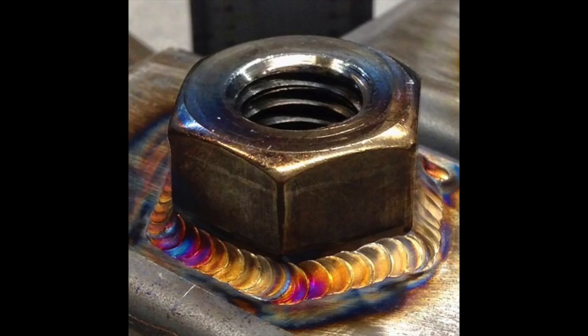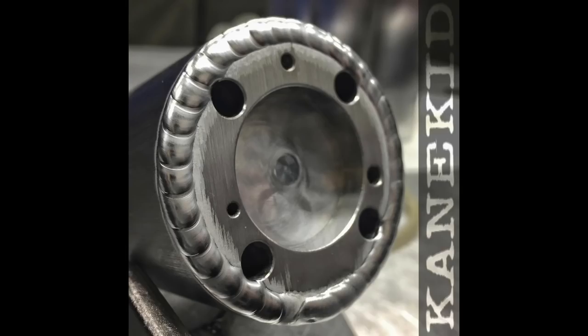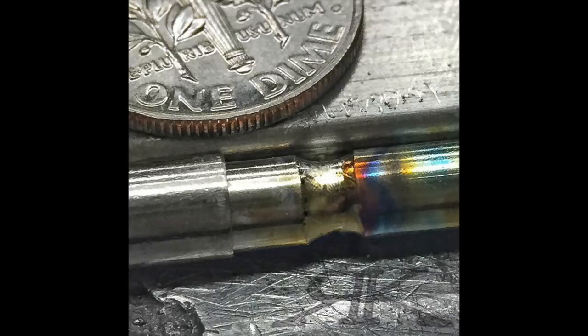I'd say if you were going to compare silicon bronze to ER70 steel wire, then yeah, it wets out that much better than 4043. It goes in the opposite direction, like 5356 as opposed to 4043, as far as wetting out better. Wow. It's like 12% silicon, and that makes not only the melt point drop, but it makes the solidification range broader, and that's supposed to help with cracking in highly restrained joints. Again, it doesn't have quite the mechanical properties, but for a lot of casting repairs, you don't wind up with the same mechanical properties anyway. Much less likely to have porosity than 4043 or other rods.